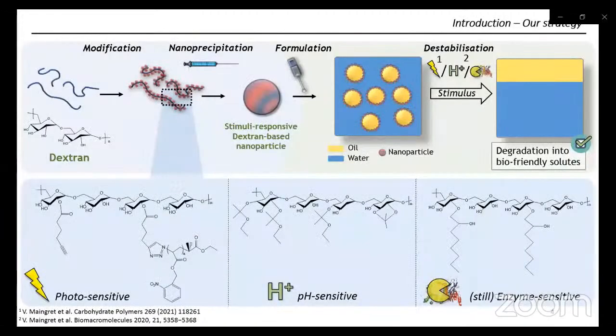To do so, we set up this whole strategy, starting from the hydrophilic polysaccharide, which we modified to bring stimuli responsiveness and also hydrophobicity. Thanks to this hydrophobicity, we were able to produce nanoparticles with the nanoprecipitation process. And using these nanoparticles, we were also able to stabilize Pickering emulsions, oil and water, and finally to destabilize them on demand thanks to the stimuli we chose: light, pH, and enzyme.